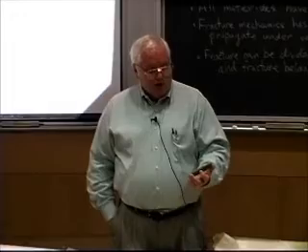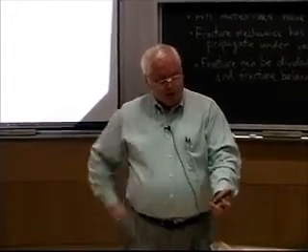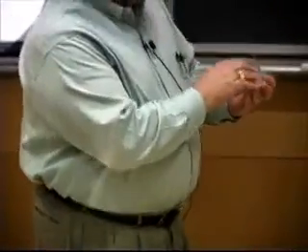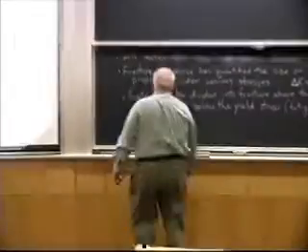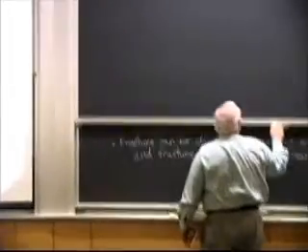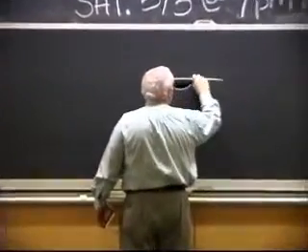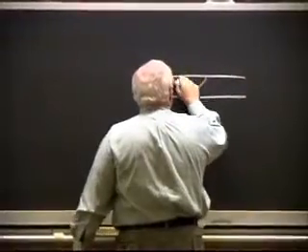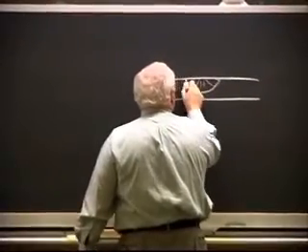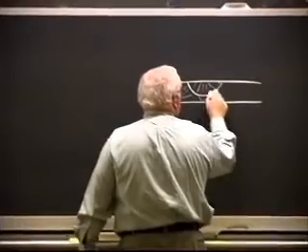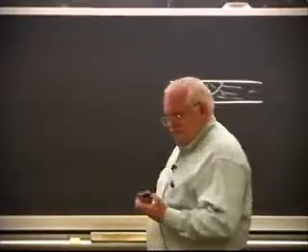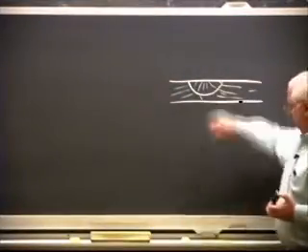It failed in fatigue. I looked at it in my dining room and I said, oh, well, there's the fracture origin right there. When I pass it around, you can see the fracture origin because I marked it right here. If you look very carefully, you'll see a little thumbnail notch, which is typical. And you actually can see it in this light. The other day in my office, which I have brighter lights, you couldn't see it, but there's a little region where you kind of have radial flaws growing there, and here you have the fatigue crack lines. Actually, this is the fatigue crack, okay?